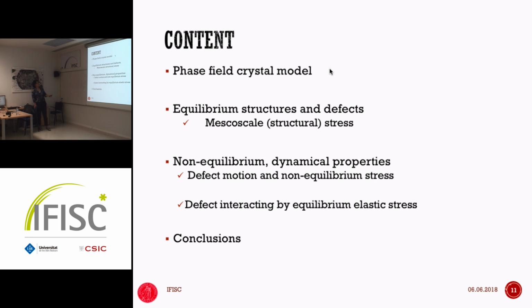So I'm going to present to you this phase field crystal model that has been around for a while, but we have taken a new interpretation of it and derived a microscale and mesoscale stress field that is going to be our stress observable. Okay, so we can calculate all of the stress-strain curve based on this stress field. We show that it has all the properties that are needed to be a mechanical stress. And then we're going to discuss, these are equilibrium properties, but then we're going to get into the non-equilibrium properties and the motion of the defects, what drives the motion of the dislocation in the stress field and in this lattice, and how they interact with each other.